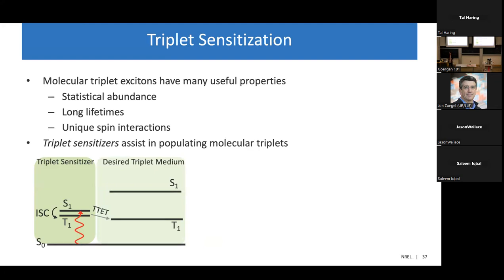Now, one of the big challenges with using triplets, especially for optical applications, is that you typically can't directly photoexcite to a triplet state because that's also spin disallowed. So what we typically do is introduce a triplet sensitizer. So that's another molecule or thing that's able to absorb light and then produce triplets with high efficiency and ideally with low energy loss.